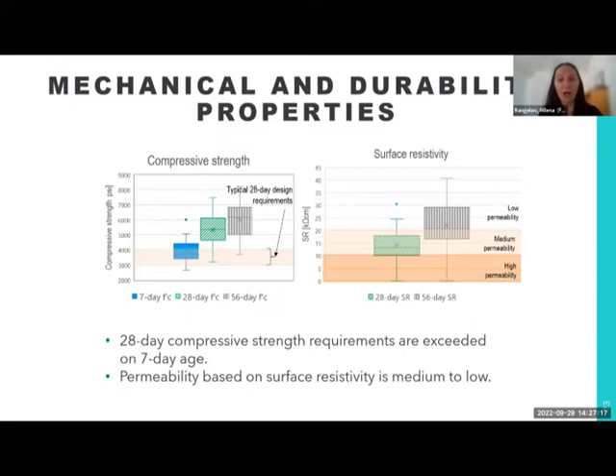When we looked into other data that they have collected, these would be compressive strengths on different test dates. And here on the left-hand side, you can see 7, 28, and 56 days compressive strength. And then the shaded area right here represents typical 28-day design requirements. We can see that most of our mixes achieve that 28-day compressive strength requirement already on day 7, and then on 28 days, compressive strengths are quite a bit higher than what is specified.